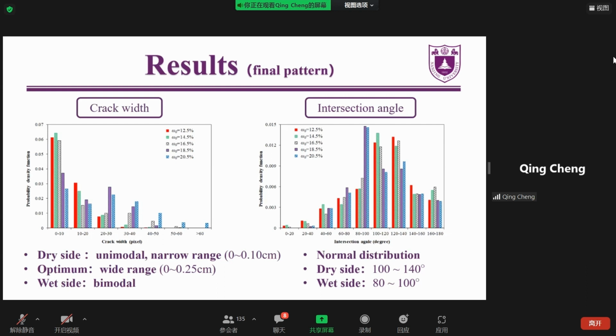Interestingly, we can find that for the soil samples compacted on the dry side and at the optimum water content, the intersection angles are mainly distributed in the range from 100 to 140 degrees. This corresponds to the observed phenomena that for soil samples with an aggregate structure, only primary cracks exist and they are formed at the same time at the beginning stage of the desiccation. And for the soil samples compacted on the wet side,